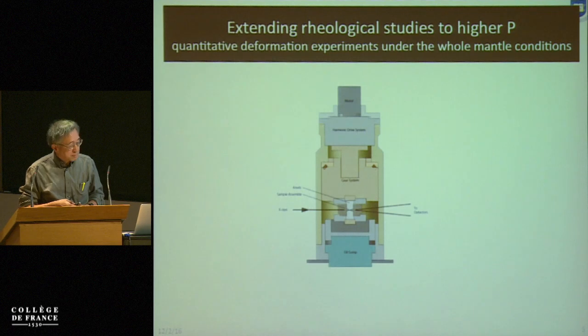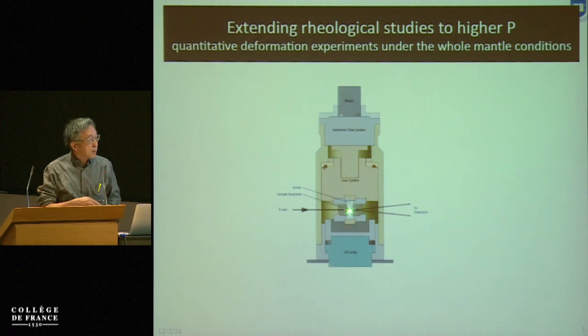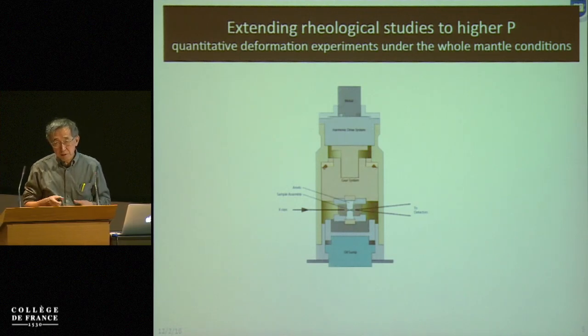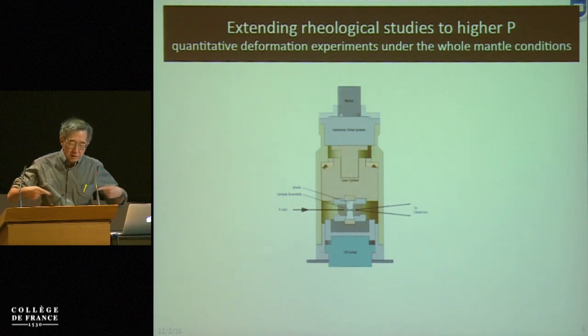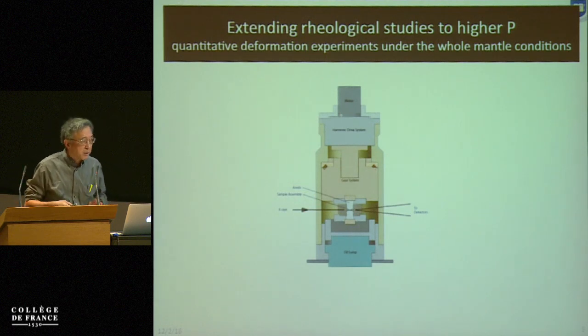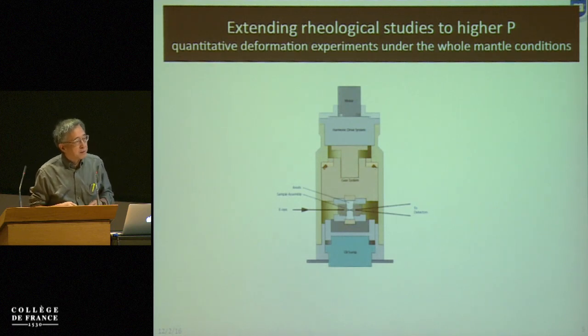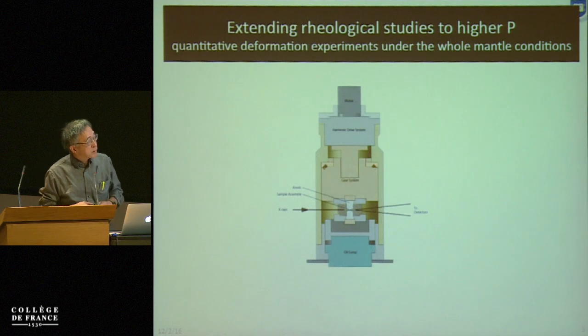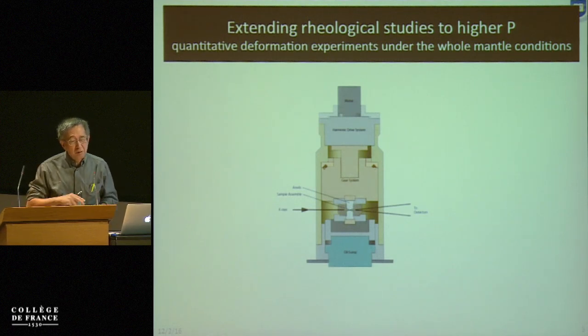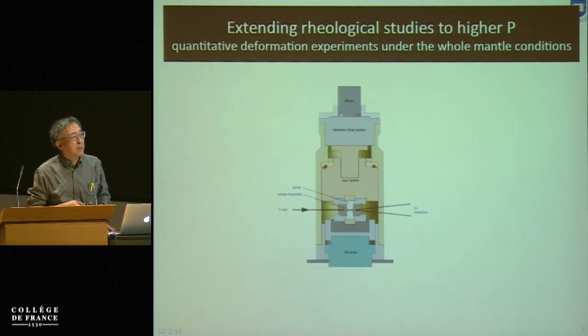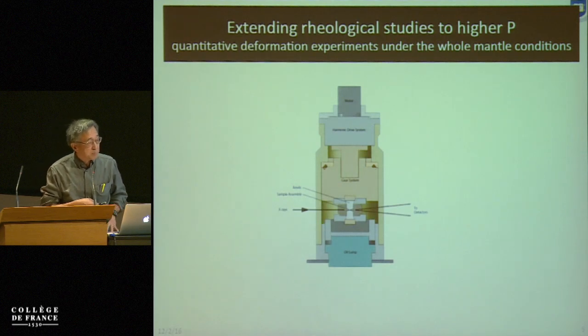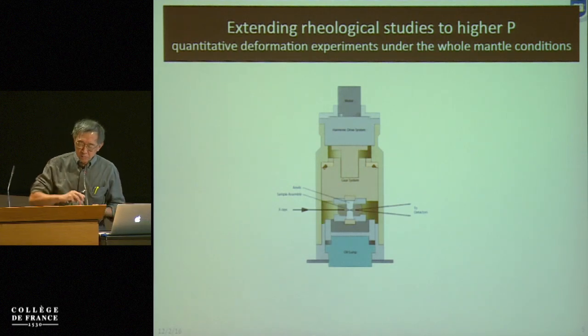The reason I chose torsion is that in torsion experiments, the support for the anvils is almost exactly the same as in static experiments, so you can go to much higher pressure in comparison to another technique, which has a moving piston going through some space. In this case, there is a very high potential for failure. So that's number one. Number two, by torsion test, at least theoretically, you could go to really high strain. In practice, high strain is challenging, so the largest strain we have reached under deep mantle conditions is 300%, but that's still pretty large.